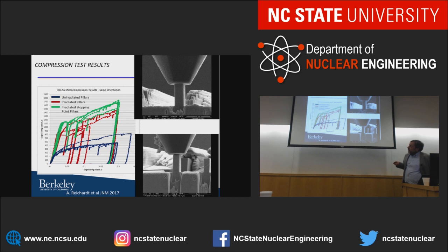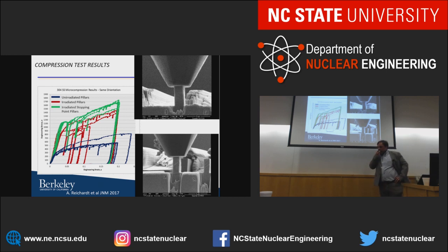So we're having our stress and strain, and this is unirradiated, irradiated, and stopping point irradiated. So of course yield strength is a lot higher. But we also observe these very distinct load drops. In the unirradiated case, nothing too exciting really happening. But in the irradiated case, as I mentioned, there's a white line coming. I don't know if you can see it. It's getting a bit brighter. And then there's another one here, which is similar to its neighbor, right? Same angles. And what happens is all that deformation happens very suddenly within very distinct slip systems. And we see that also in the stress strain curve associated with specific load drops. So we were interested in that.